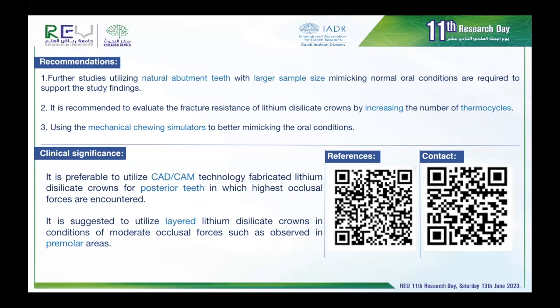Thank you, Dr. Afra, for your question. Yes, actually, the literature is very rich in studies that proved and shown clearly that the CAD/CAM monolithic ceramic crowns have greater fracture resistance values than the other groups in their studies. However, they utilize different ceramic materials. The one I can recall is a study published in the Journal of Prosthetic Dentistry, which is a famous dental journal with a very high impact factor. In that study, also the CAD/CAM group was the highest fracture resistance value group, but the material of fabrication was the feldspathic ceramic.